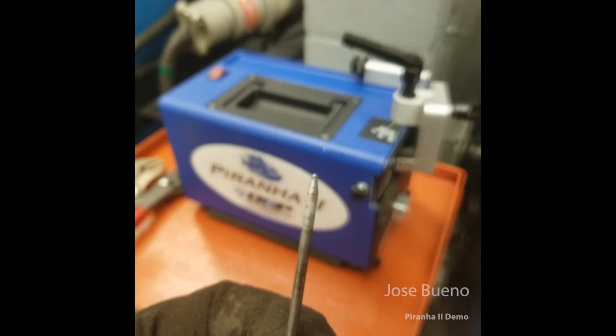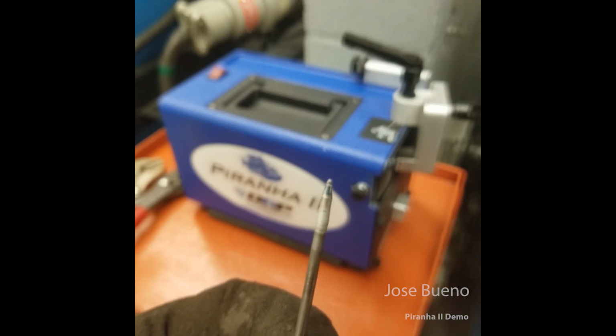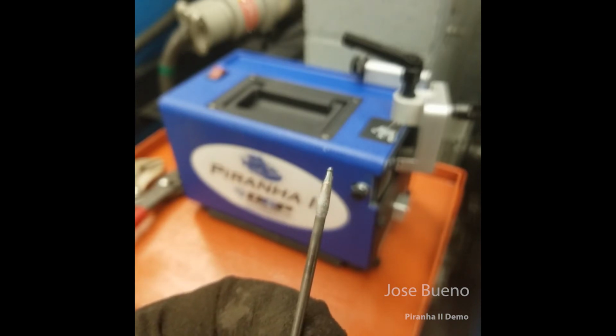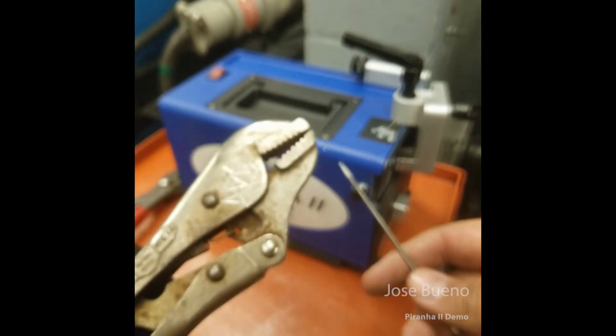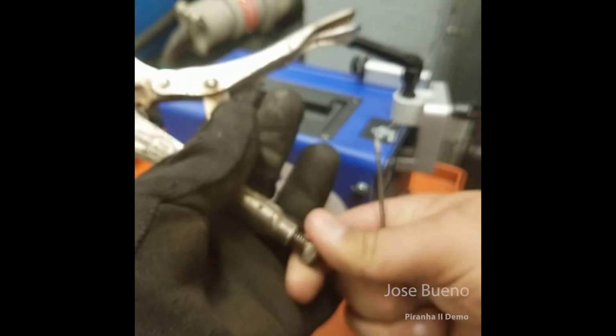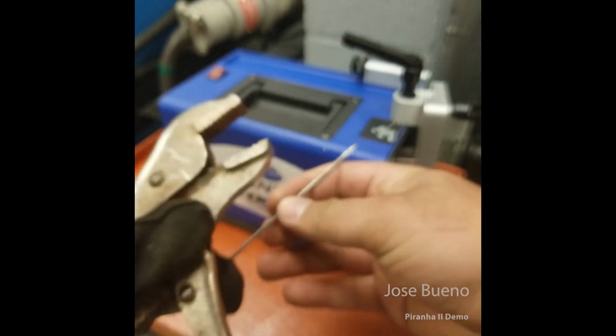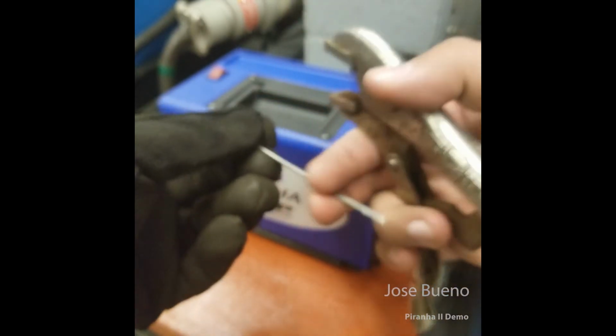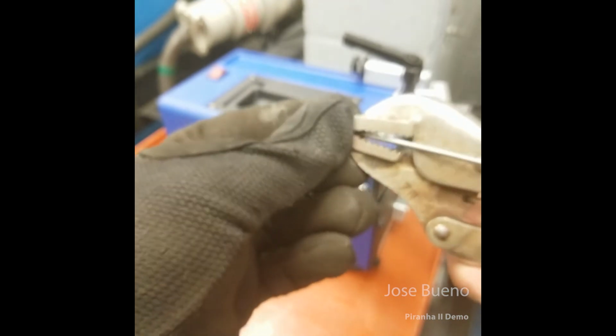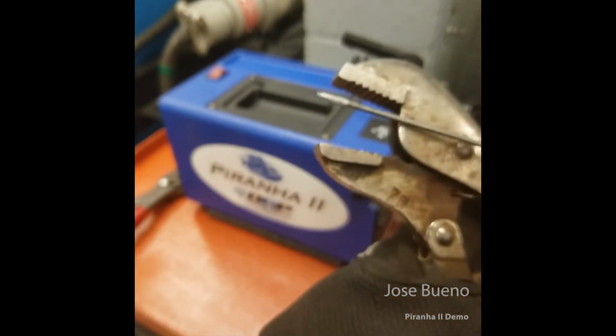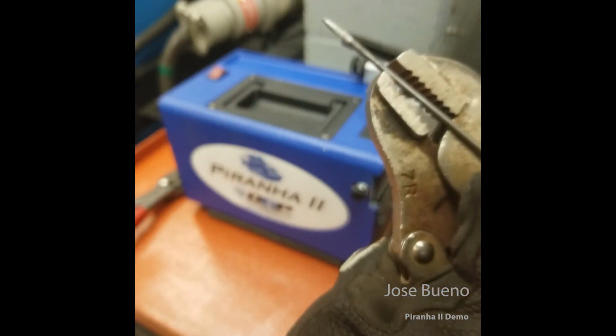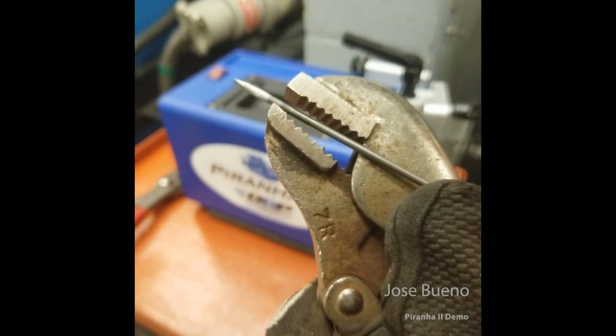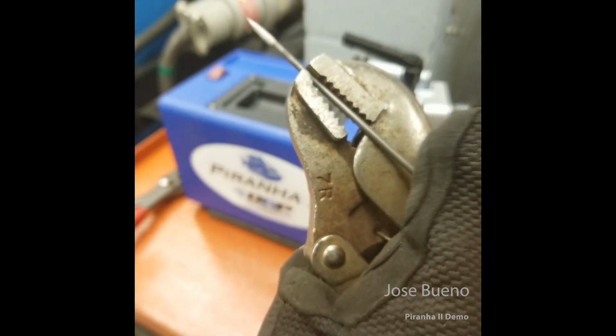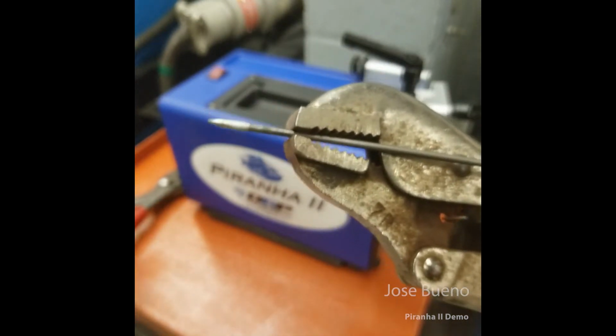So, for one, let's take this example. This tungsten electrode was contaminated while welding on aluminum. One method of preparing the tungsten for grinding is to remove all of the contaminated portion of the tungsten. An older method to do this was to clamp a vice grip down just before the beginning of the contaminated area of the tungsten. So clamp down your vice grips right about there, and then come in from the other side with a pair of pliers or another set of vice grips, and as fast as you can, just give it a nice snap, break that end off of the tungsten, and then go ahead and stick it in the grinder to put another taper tip on there.